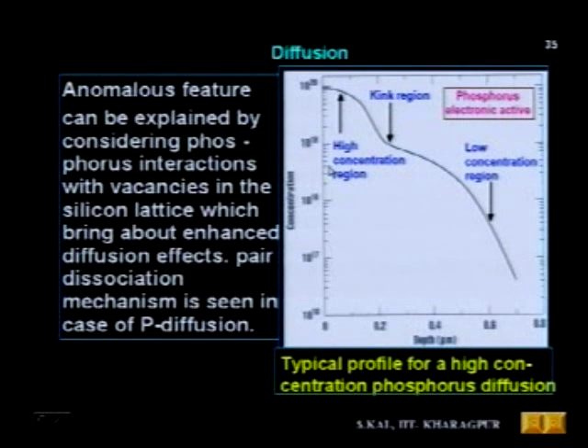And the experimental diffusion profile also shows this sort of nature. There is some flat region followed by a kink. I will show some of the diffusion profiles in the next view graph. There also you can observe that. The concentration plotted here is the electronically active phosphorus atoms, not the total phosphorus atoms. Okay.